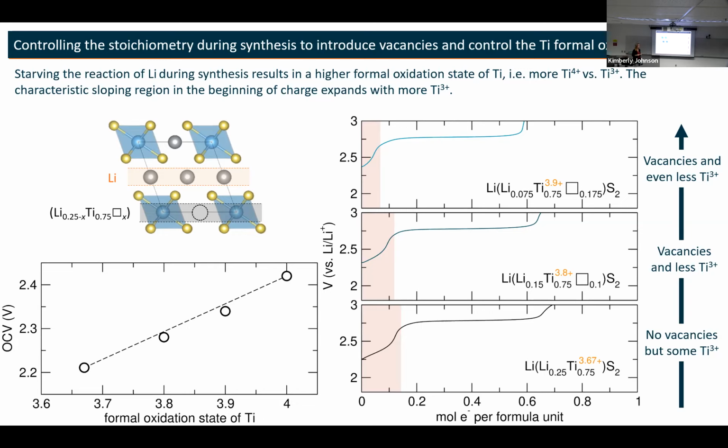Well, it depends on which energy density. So the theoretical would assume full dilithiation. So the theoretical numbers that I showed. Maybe they were talking about the Li2RuO3 slide and the LiCoO2 slide. Yeah, so those energy densities were assuming full oxidation, which is not always practical. So in LiCoO2, lithium cobalt oxide, you only get half the lithium out before you get a phase transition. So it's not possible to do that. That's why you have to substitute the metals.